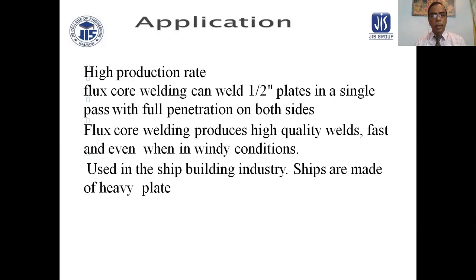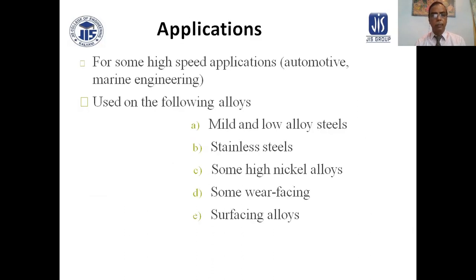Application: high production rate. Flux core welding can weld half-inch thick plate in a single pass with full penetration on both sides. Flux core welding produces high quality welds fast, even in windy conditions. Used in the shipbuilding industry, ships are made of heavy plates. Applications: for some high-speed applications, automotive and marine engineering, use on the following alloys: mild steel and low alloy steels, stainless steel, some high nickel alloy, and some wear facing surfacing alloy.